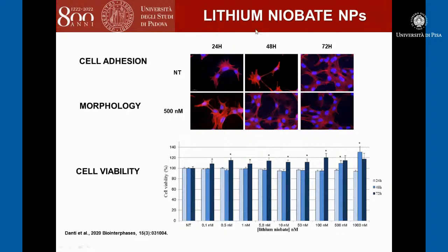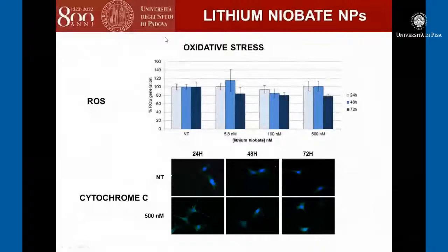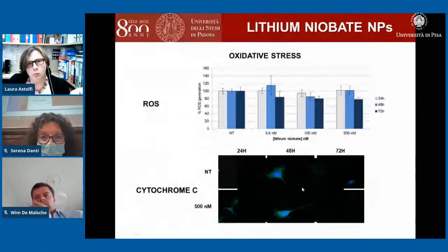About the lithium niobate, the viability again shows that there is no toxicity at all the doses and times tested, and as reported in the literature, also in OC-k3 cells, the lithium niobate increases the cell proliferation. About the cell adhesion, so the morphology, again we have a good organization of the cytoskeleton and a healthy condition of the nucleus. Oxidative stress wasn't detected, and again the cytochrome C stayed inside the mitochondria. So both lithium niobate and barium titanate are good, biocompatible nanoparticles that can be applied to the PVDF.